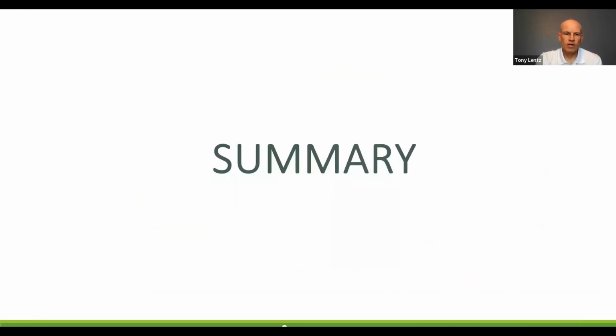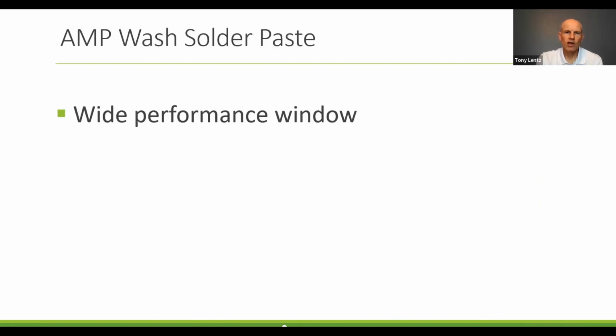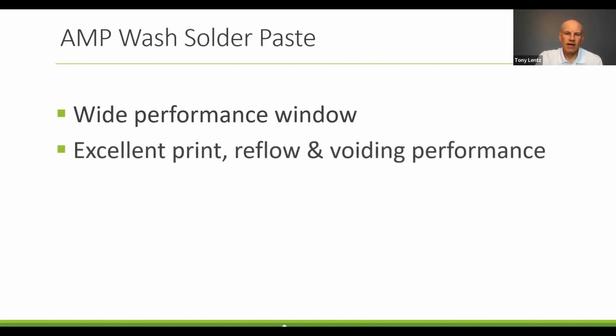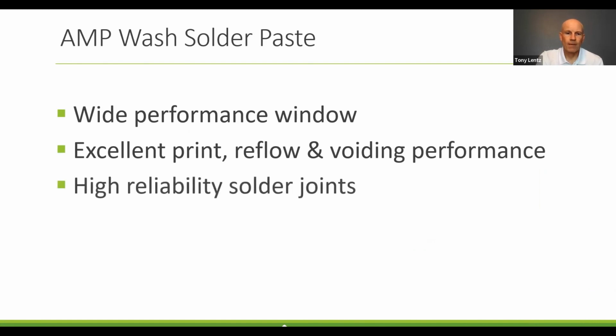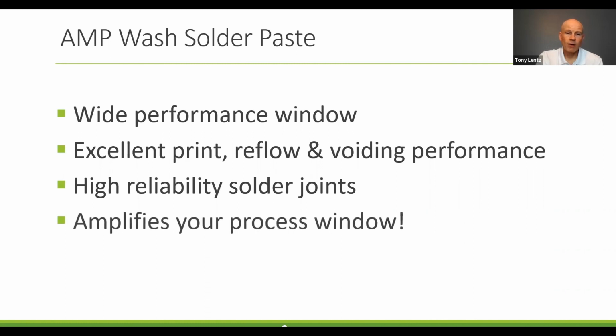And so by switching to TempSave B37 for their second side, they were able to reduce the profile significantly and avoid melting those SAC305 solder joints that were on side 1, which was facing down in the oven. So that's one advantage of running these low temp solders. Well, that brings us to a summary of everything I've talked about. So AmpWash solder paste was designed to have wide performance windows in both print and reflow. It definitely has excellent performance in those areas and even exceptional voiding performance. We would call this an ultra low voiding solder paste. It definitely has the ability to give high reliability solder joints if you choose the higher reliability alloys that I've been talking about. And it can amplify your process window.